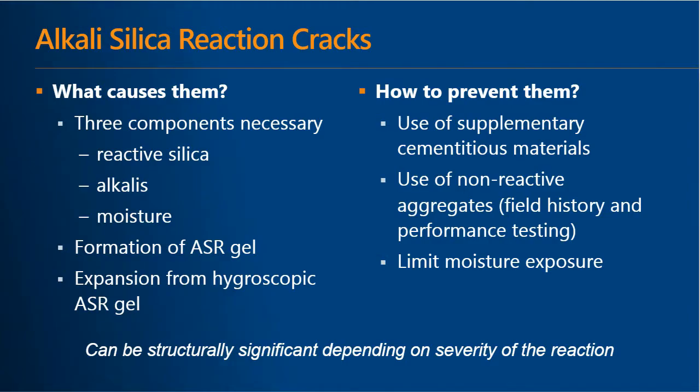What happens is the silica reacts with the alkalis, and it forms what we call ASR gel. This ASR gel is hygroscopic, meaning it loves water, so any moisture that is around, it's going to imbibe into its structure, swell, and eventually cause cracking. There are many, many ways to mitigate ASR. You can use supplementary cementitious materials. You can use non-reactive aggregates. You can limit moisture exposure. And again, they can be structurally significant depending really on the severity of the reaction, the severity of the cracking, and the type of element that is exhibiting cracking.